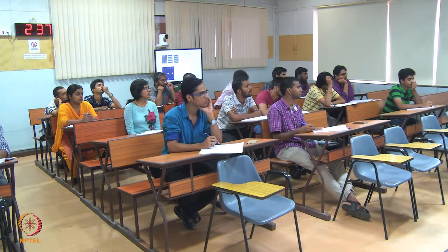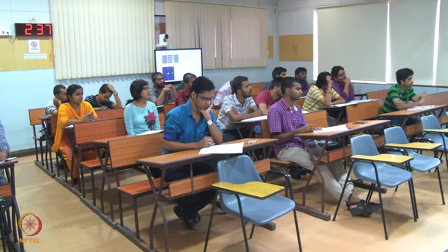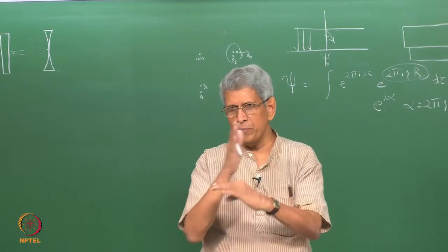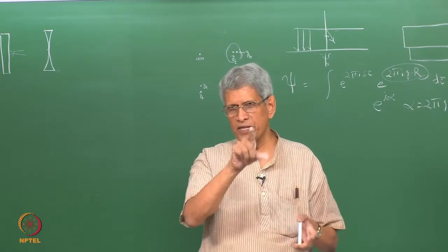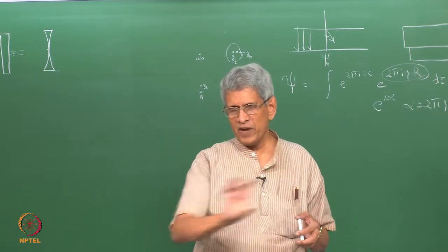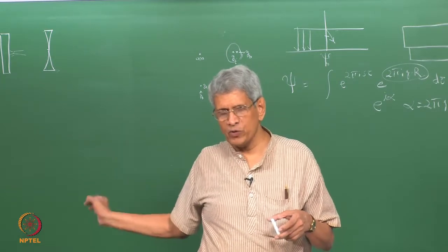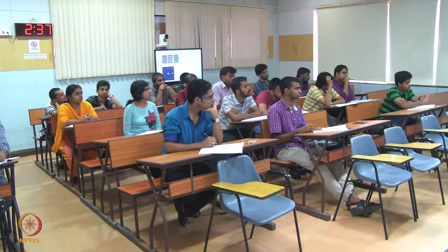Yes, sir. As far as the Moiré fringe is concerned, there are only two spacings, because when we calculate the intensity, the same beam, as it passes through as a parallel beam, will give a diffraction pattern from the top layer and a diffraction pattern from the bottom layer. Both are independent, coming very close by. The top layer has one spacing and the bottom layer has one spacing. That's it. There's no change in spacings, that's not changing.